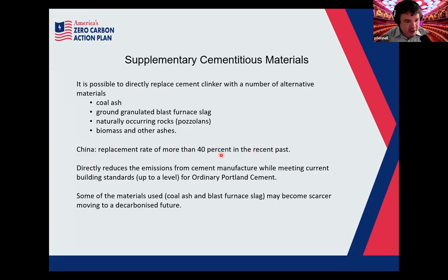China was replacing up to 40% of their clinker with supplementary cementitious materials, these additional things. That was leading to issues with the cement quality, so they have now rowed back, and globally the replacement rate is coming up to about 30%. So you don't want to replace too much of your cement clinker with supplementary cementitious materials, because it may make your cement worse. But you want to replace as much as possible,